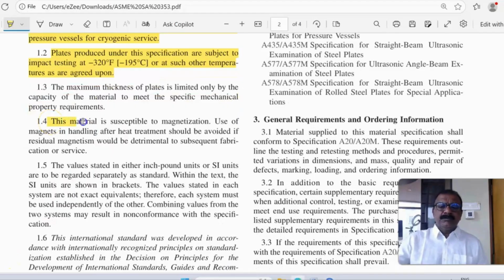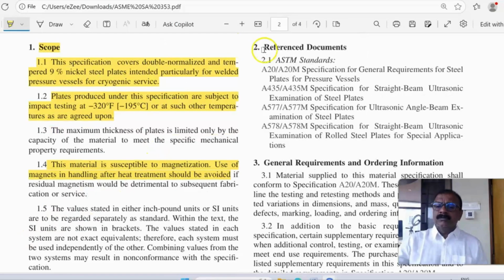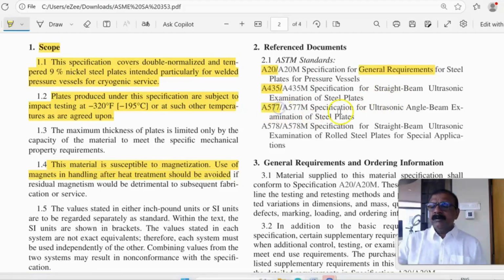This is important. This material is susceptible to magnetization. Use of magnets in handling after heat treatment should be avoided, or else we will face the problem of arc blow during welding. Then ASTM reference standard A20 for general requirements. Then A435 is for straight beam ultrasonic examination, and A577 for angle beam examination. Also A578 is important because this is a specialized specification for straight beam ultrasonic examination of rolled steel plates for special applications.